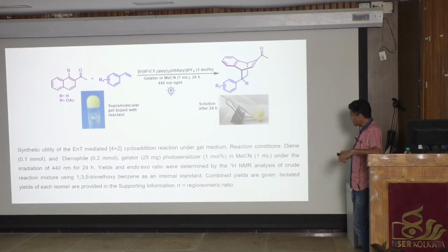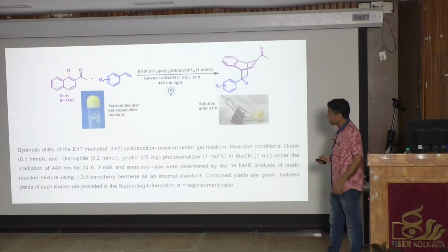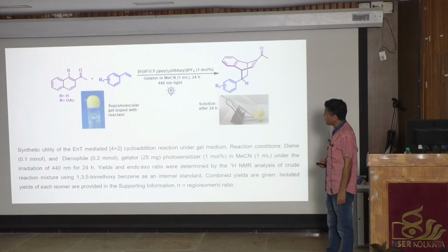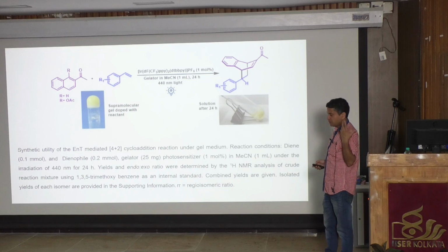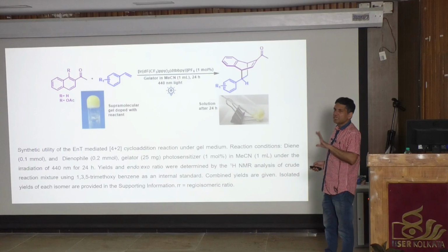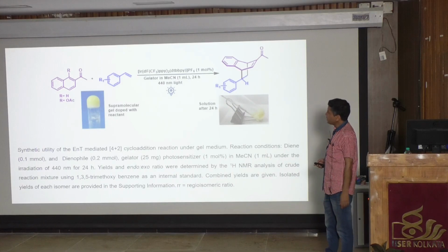So then we thought, okay, let's do the reaction. We have taken our gelator in acetonitrile. We just used that acetonitrile from our solvent purification system, with no degassing, nothing. Then we put all our materials together with this catalyst, and then we just sonicate it. Immediately it forms a gel, and due to this catalyst, it now looks a little bit yellow, otherwise the gel is white in color.